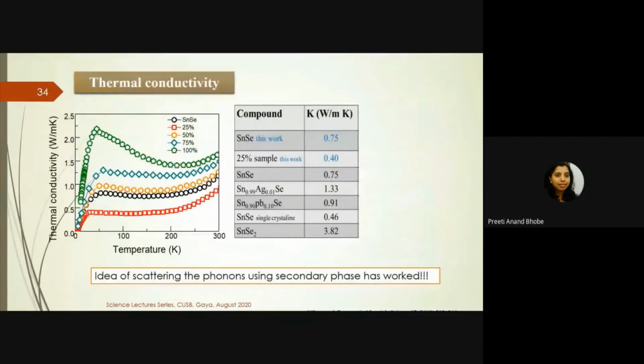The interesting property is that the thermal conductivity is decreased. So here you have the black curve, which is the pure SnSe. You put 25% of SnSe2 phase in this, and the thermal conductivity is further decreased, which is very good news. The thermal conductivity decreases, our ZT will increase.